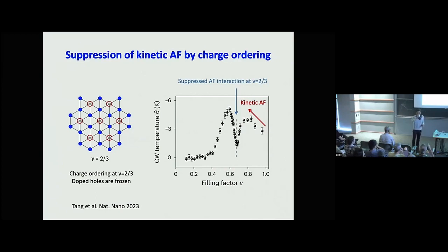Yeah. You were showing this Curie-Weiss temperature enhancement with doping. I'm not sure how to interpret it. It's true that the holes, in some sense, mediate some antiferromagnetic interaction, but first of all, there are not so many of them, so I would not view this as an overall antiferromagnetic interaction between all the spins. You're measuring a Curie-Weiss temperature whose magnitude is supposed to come from every electron. And it's also weird, it's metallic in this regime. It's a metal, right? So the straightforward interpretation as Curie-Weiss is questionable. But if you have a very small Fermi energy in the system, if it's a metal, then you could get a... So is the Curie-Weiss temperature also...